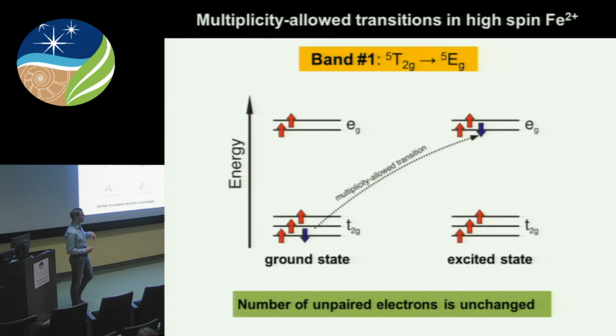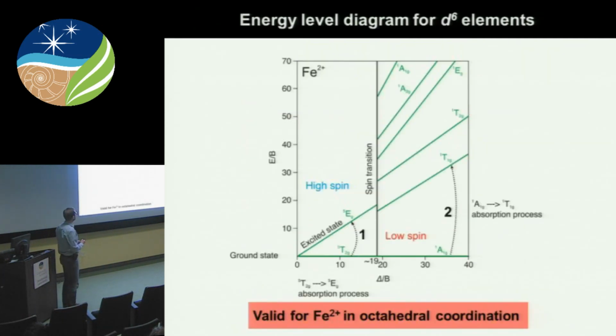So the selection rule that we're mostly interested in is the so-called multiplicity selection rule, which basically states that upon the excitation process in your mineral, or any material, in fact, the multiplicity, or simply the number of unpaired electrons, should be preserved. So you can count unpaired electrons here. So 1, 2, 3, 4. We excite this electron from the T2g level to the Eg level, and we end up having 4 unpaired electrons again. So this is a multiplicity allowed optical transition that gives us an absorption band. So only allowed transitions theoretically should give intense absorption bands in the spectra.